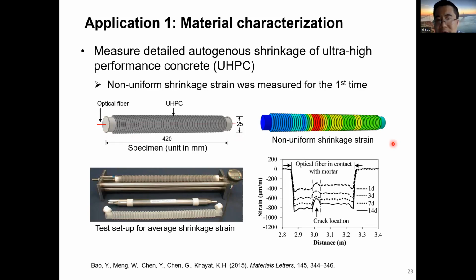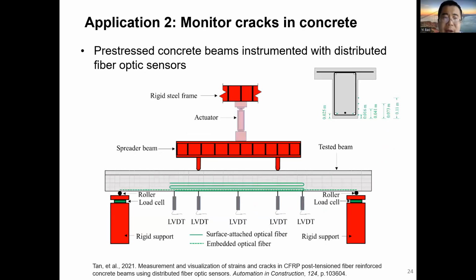And we found that, in fact, the autogenous shrinkage in mortar is not uniform, and there are many factors that could cause this non-uniformity. What we can see from this figure is that the shrinkage strain can be different along the length of the specimen, and also we detected a micro crack from the strain distribution. After the testing, we cut the specimen, and indeed we found a small crack there. But according to the previous method, we will overlook those effects and therefore generate a very large scattering of data. But with this method, we can better characterize materials.